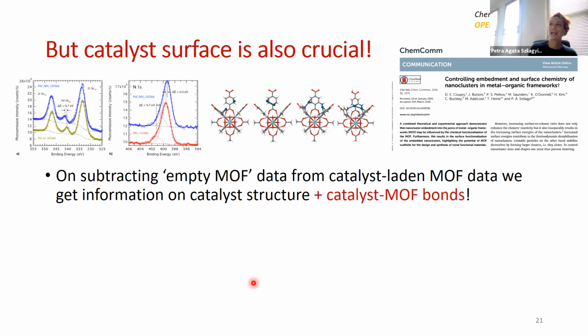Now, there are two things I omitted previously. The first is when I first discussed briefly the usability of pair distribution function analysis. I think I was a little bit hand-wavy when I said that as we subtract the total scattering data of the empty framework from the total scattering data of the guest-laden framework, you basically get to see the atomistic structure or the short-range order within the guest particles. So this is true, but not the whole truth, because we see everything that is not present in the empty framework. So we see the guests as well as any host-guest interactions.